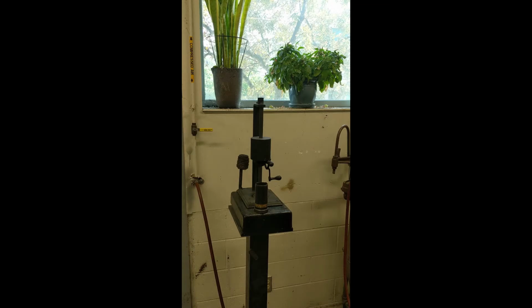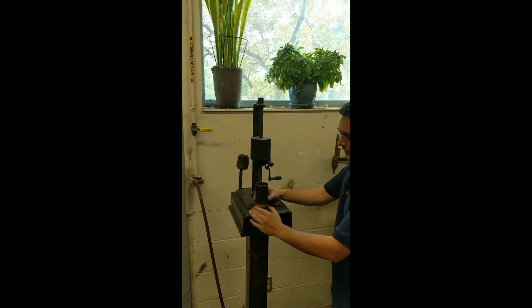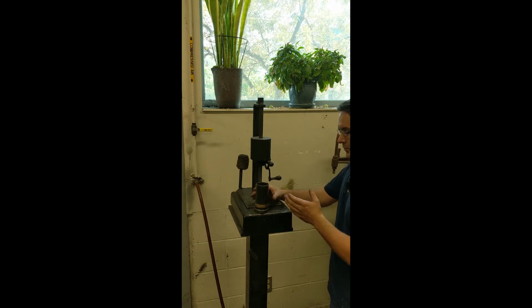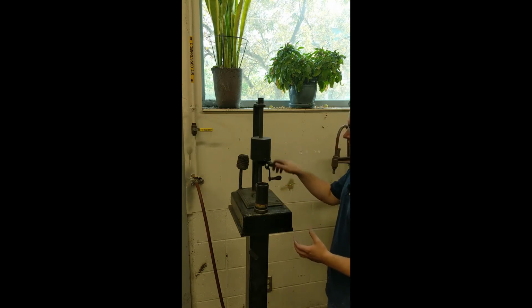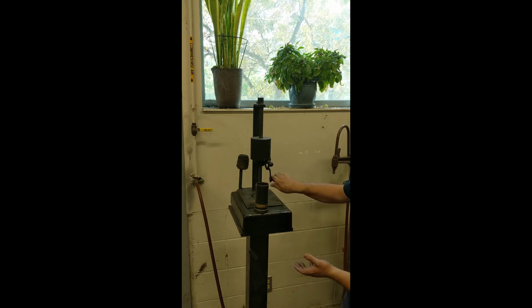One of the important characteristics of green sand is its ability to take on moisture and to become compactable. And we have to be able to evaluate that compactability because it's an important part of preparing the media for the mold making process. It's important for us to know how compactable the sand is because too much moisture will lead to gas defects as that added moisture meets the molten metal, and with too little moisture, the sand won't be compactable enough, it won't be strong enough to take shape against the pattern plate. So this test is a test of compactability of the sand.